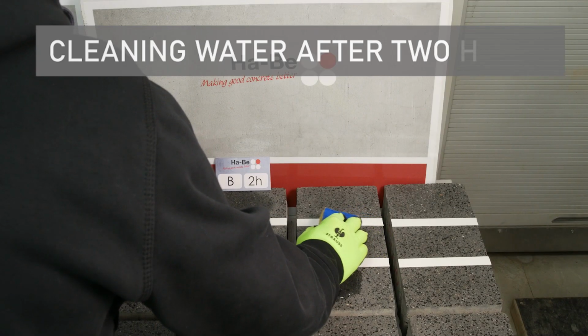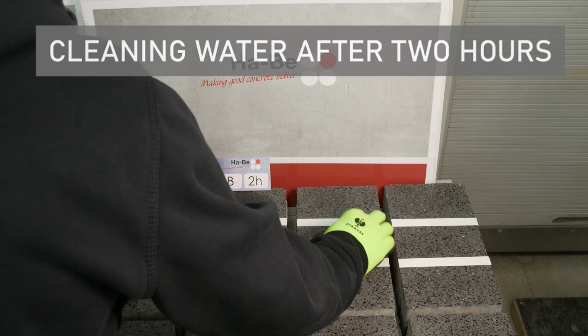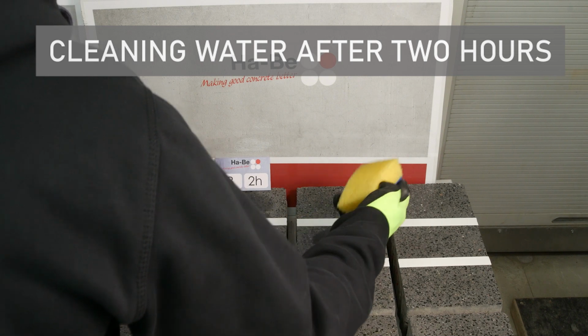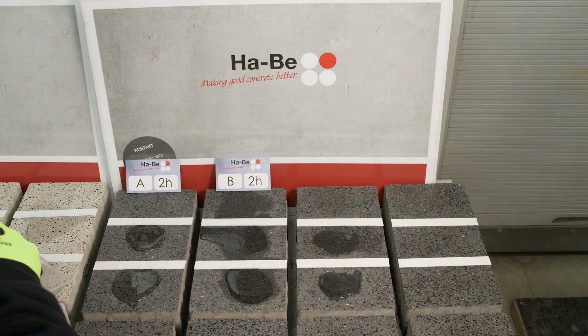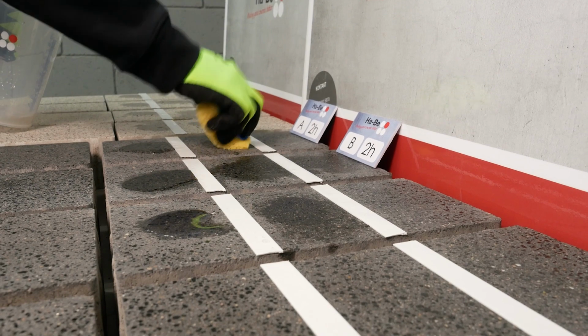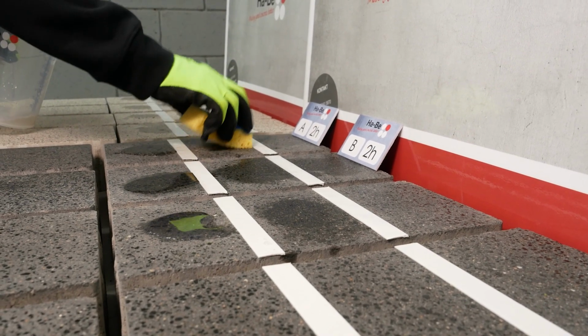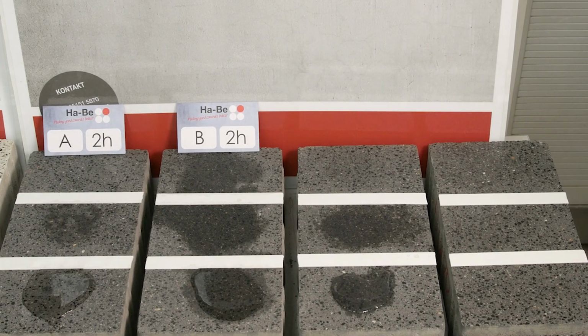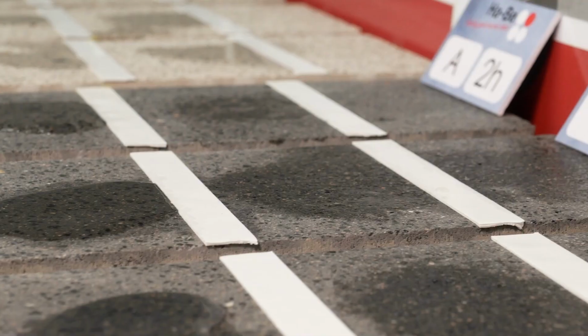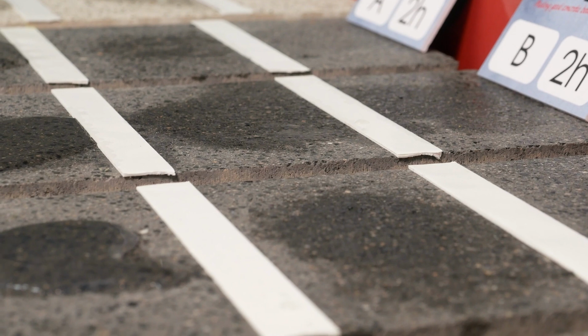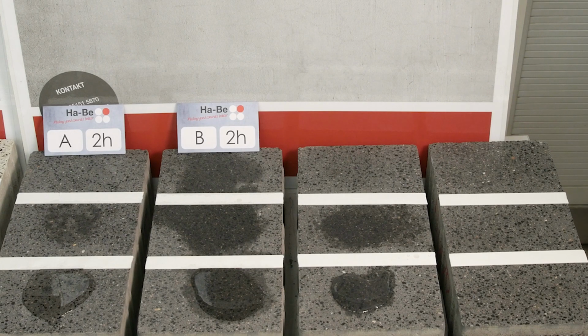Let's remove water after 2 hours of exposure on the colour mix and polished concrete series, and watch the process of water stain formation. The smallest stain on sample 1. On sample 4, water is completely absorbed by the base. Samples 2 and 3 have visible water stains. Now we have to understand how deep these spots are. To do this, let's observe the change in the water spots for another hour.